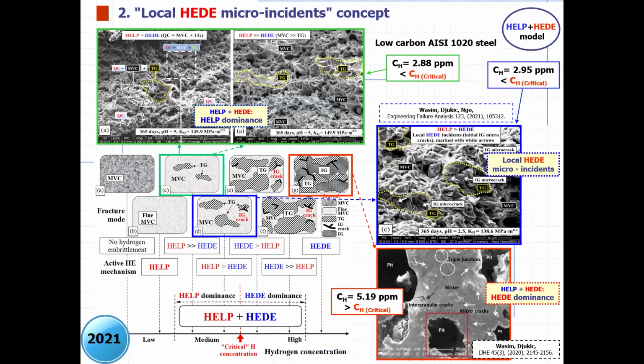After that, here is the overview about local HEDE microincidence, which means that we have initiation of the HEDE mechanism even in the case of relatively low hydrogen concentration in the material, and after accumulation of large enough HEDE microincidence, we have, microscopically speaking, the transition between ductile behavior of the material to pure embrittlement, which means a sharp drop of ductility of the material after accumulation of that mechanism. But this is a continuous process, and we must map and investigate when HELP and other plasticity-mediated mechanisms are predominant and when we have a transition to the decohesion HEDE mechanism.